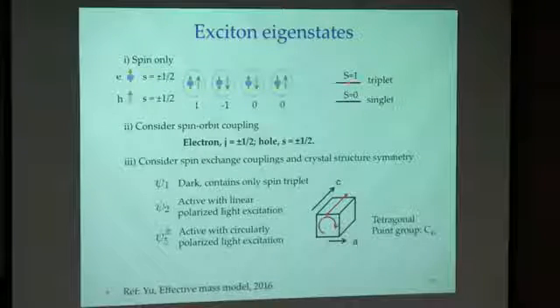Optically, only singlets are bright states because the angular momentum is not directly exchanged between the photon and the electron spin. You need spin-orbit coupling. So of course, we consider spin-orbit coupling, and that's a big effect in this material. When we consider spin-orbit coupling, the electrons are actually represented by J states, not spin states anymore. J is now a good quantum number. The hole still stays as S-like.